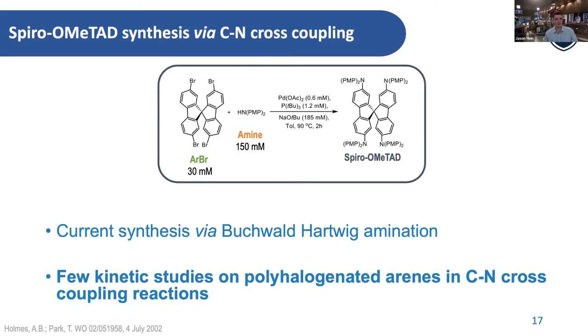How it's currently done, one of the best-case ways, is to take this tetrabrominated starting material and execute a Buchwald-Hartwig C-N cross-coupling. What it means is you've got to get four C-N cross-couplings to happen around that periphery very cleanly. For anybody who's executed these C-N cross-couplings, if you don't get your ligand right, if your catalyst turnover is poor, then there can be issues of dehalogenation or halted or rested cross-coupling, which may mean that you could have those failure events multiplied at every one of those sites. This can be a very ugly mix of byproducts if you don't get the catalysis working cleanly.